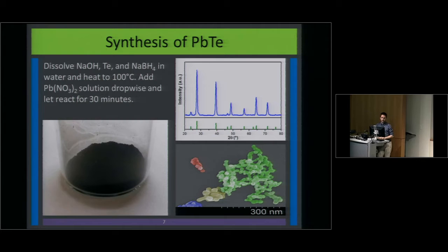You basically have a dissolved solution of tellurium metal with a reducing agent, and then you add your lead dropwise to that. So you have Te2 minus and Pb2 plus. That reacts for a little bit and forms this nice black lead telluride powder.